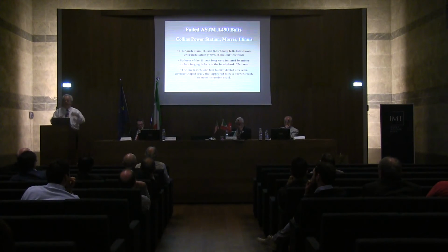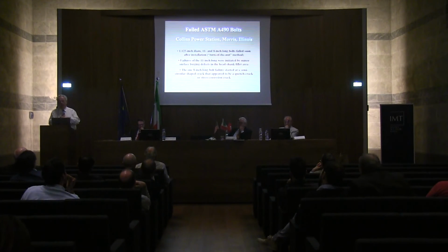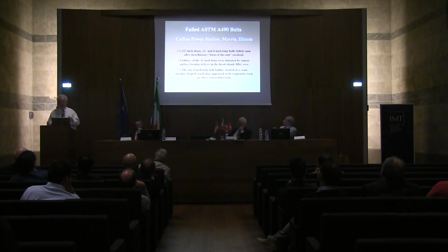And the standard practice is the next day, someone comes in with a hammer and taps the heads of the bolts, and these fell off. This is very bad, obviously, right? So they had failures of 11-inch long bolts that initiated by minor surface forging defects in the head shank fillet area. And one 8-inch long bolt started out a semicircular shaped crack that appeared to be a quench crack or possible stress corrosion crack. So ASTM A490 is 4140 alloy steel. The bolts were used in a girder splice. The temperature of installation was 20 to 40 Fahrenheit when they did the turn of the nut method.